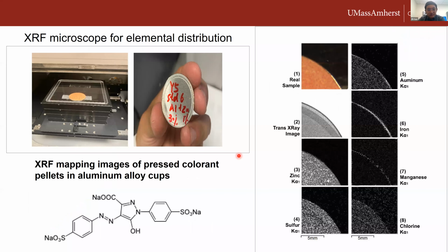As you know, we recently installed this XRF microscope in our core facility, and this microscope can give us more profound information based on different element channels. In this case, we have an artificial colorant, which is yellow 5, and we manually spiked aluminum and zinc in it to mimic the artificial lakes. This sample is scanned under the microscope, and as we can see here, we have different responses under different element channels. Here we have aluminum, iron, and manganese.